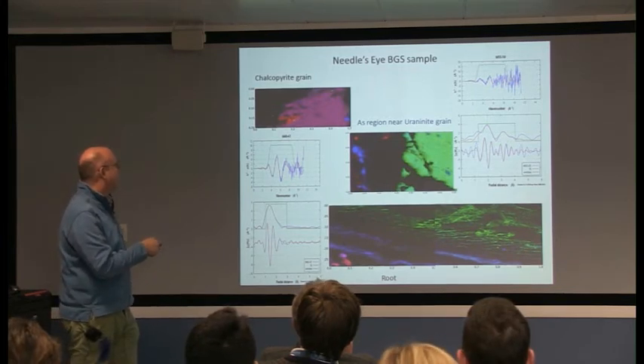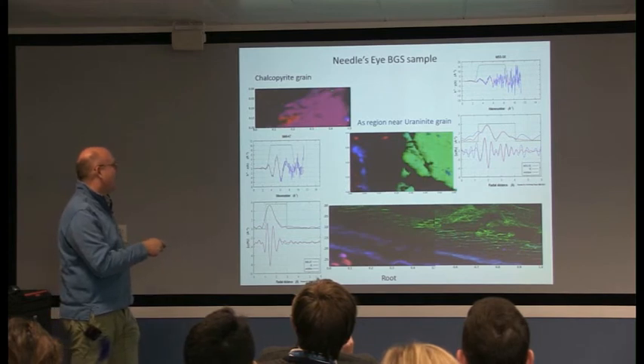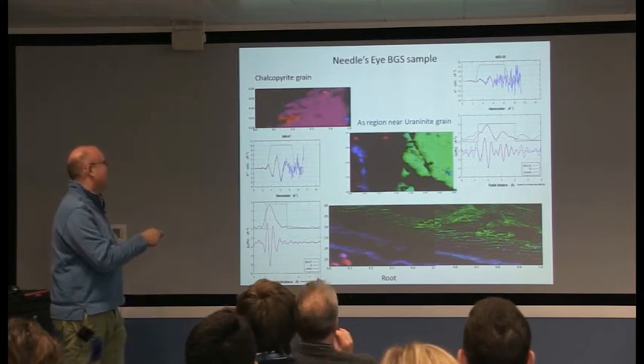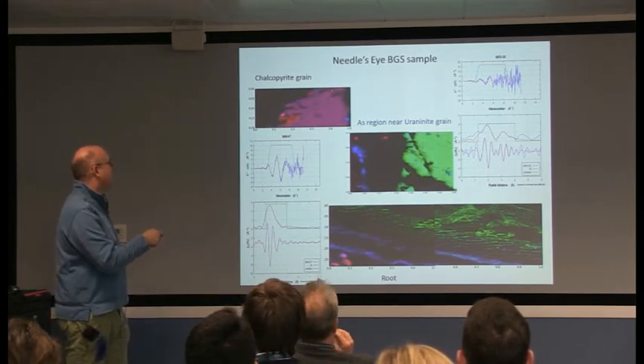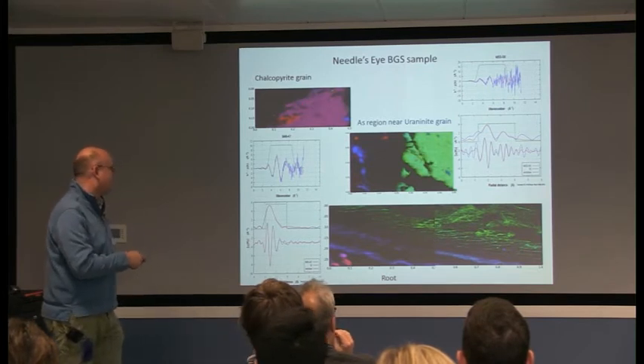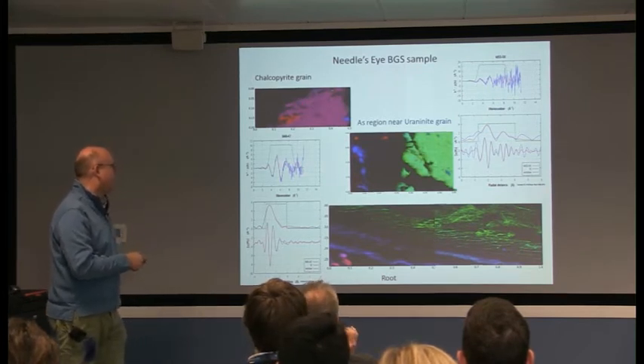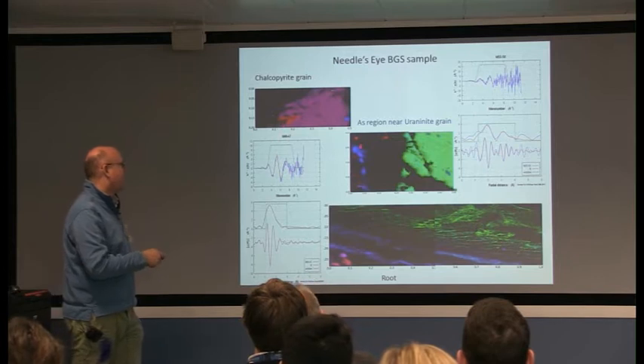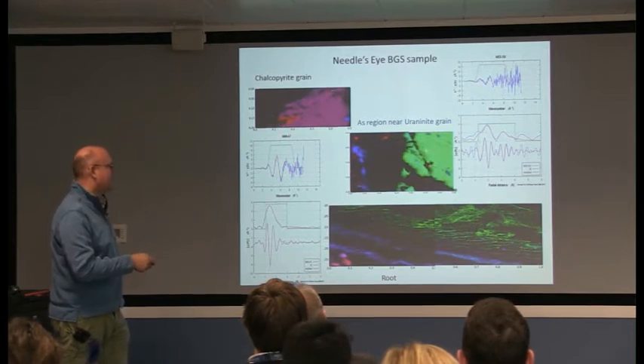Here I think we've got iron in red and copper in blue, and there's a chalcopyrite grain which has a little bit of uranium on the outside. We also collected some uranium from the edge of the chalcopyrite and near the arsenic region, and also in this uraninite grain.